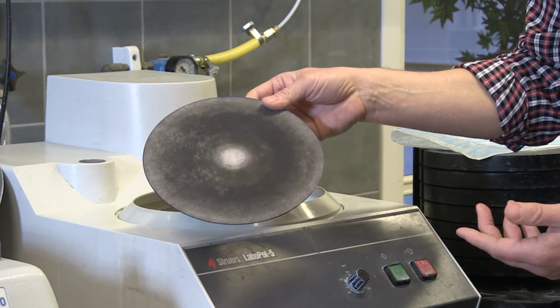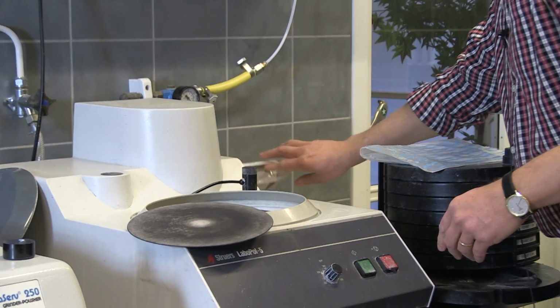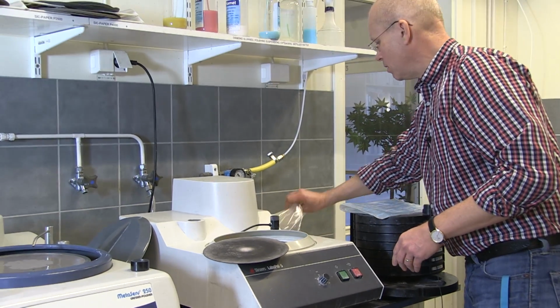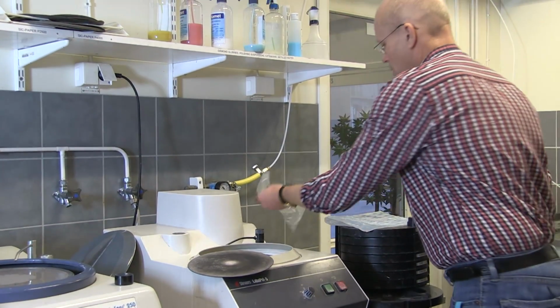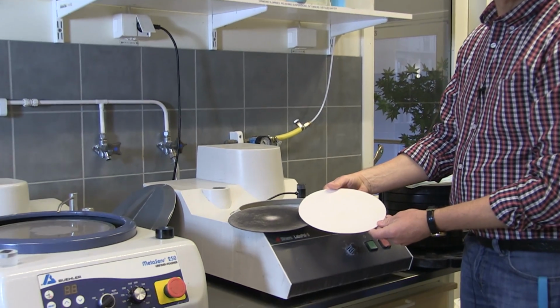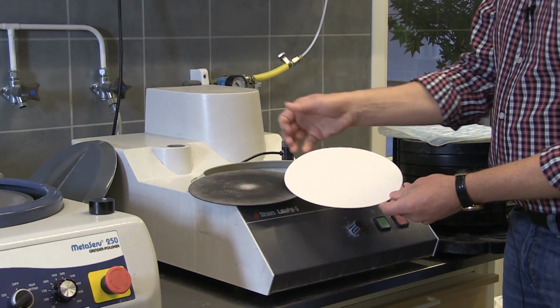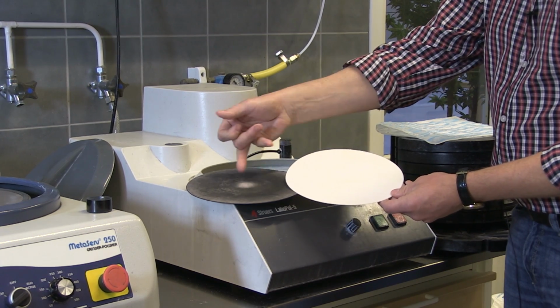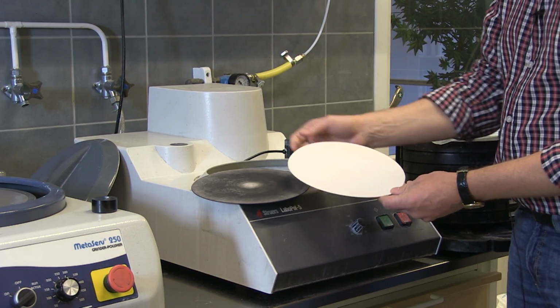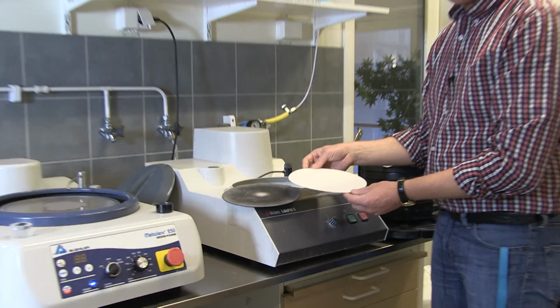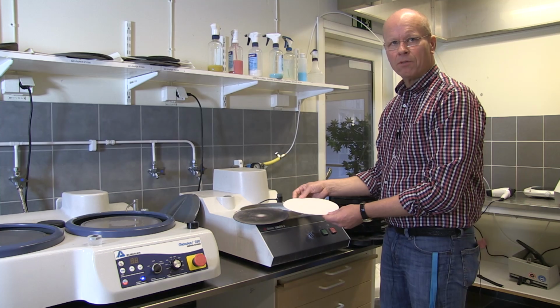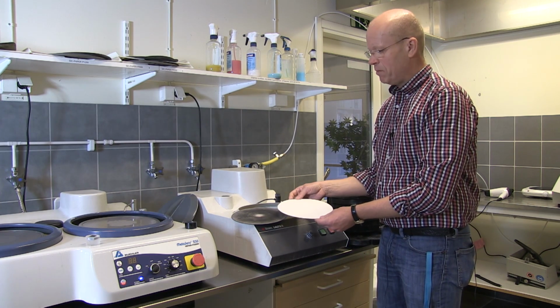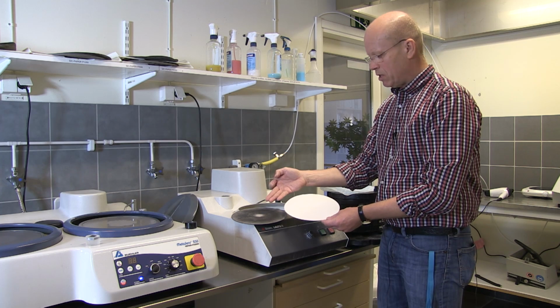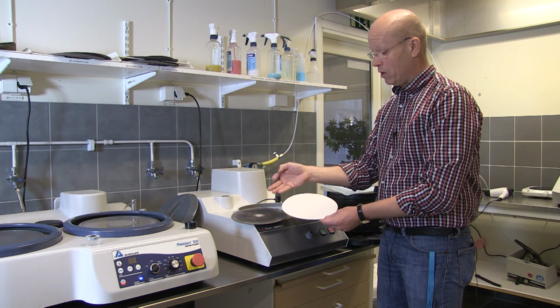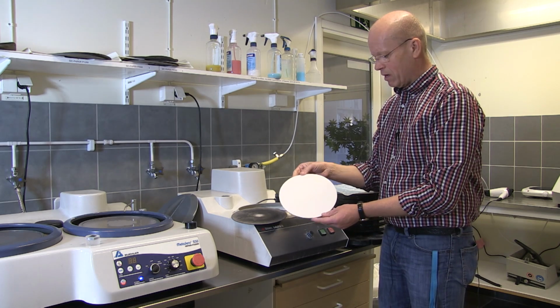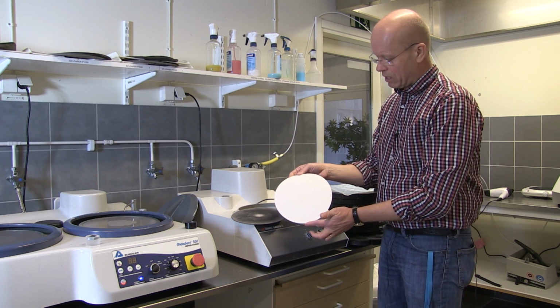I would like to show you how a new cloth looks. I have prepared it back here. I have a new cloth, and a completely new one looks like that. This contaminated cloth works very well for polishing, even though it looks like that. It works very well if previous users have cleaned their samples properly between every step. If they haven't been cleaning the sample, they will transport particles to this cloth that are much bigger than 9 micron, and it will not work. But with proper cleaning, it works very well. But just to let you know, a new cloth looks like that.